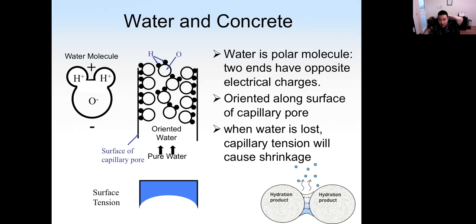The water molecule is a polar molecule, which means it has two ends, and the two ends have opposite electrical charge. And because of that, the water molecule will orient along the surface of the capillary pores inside the compound. And when water is lost, we have capillary tension, and that will cause shrinkage of concrete, as we discussed in lecture number 11. So we did that Tuesday this week. So shrinkage is caused by capillary tension. That is because water is a polar molecule.